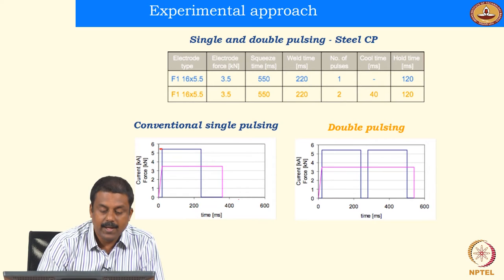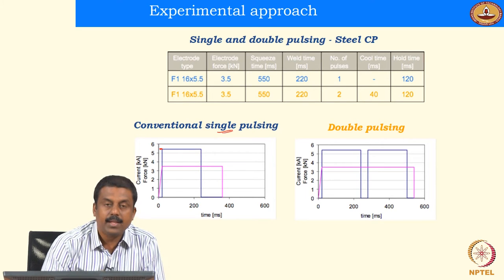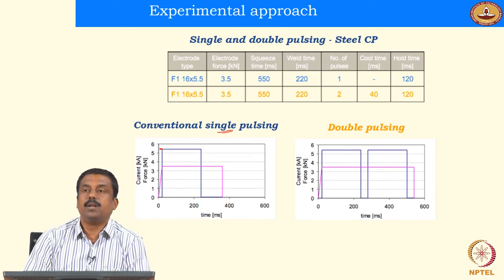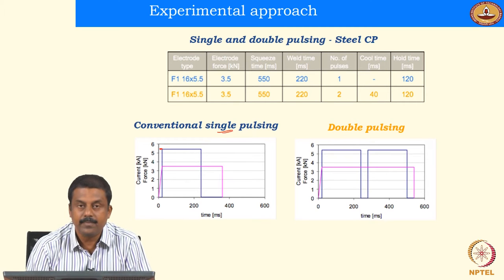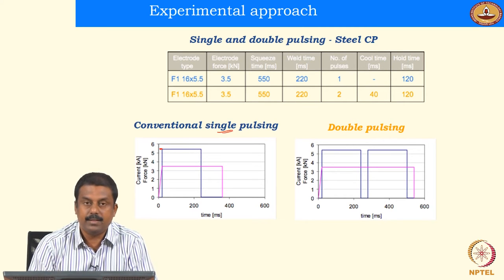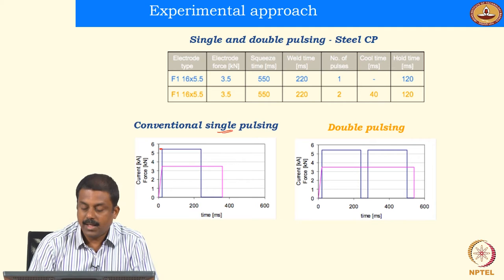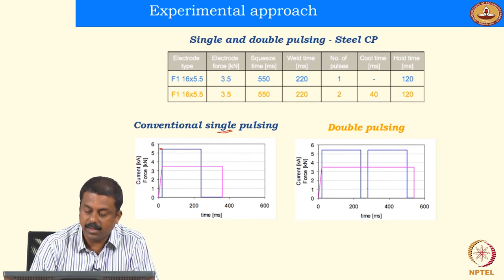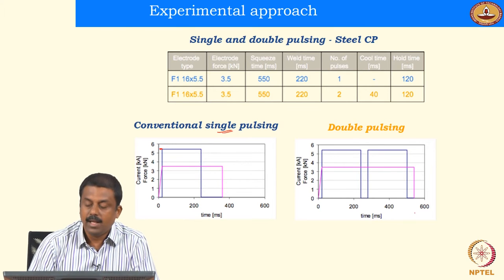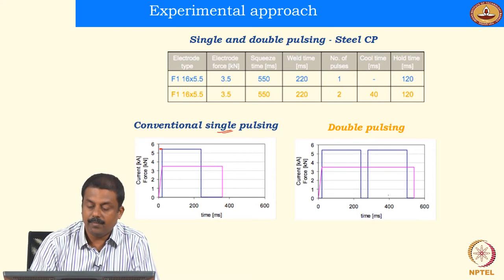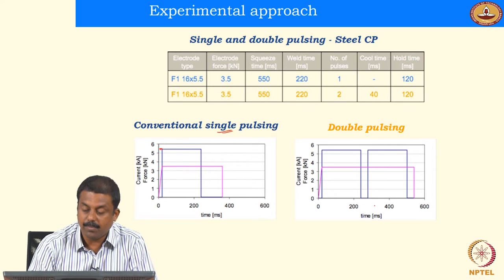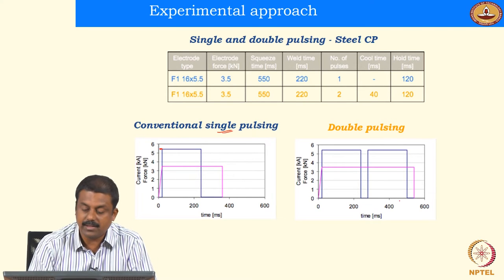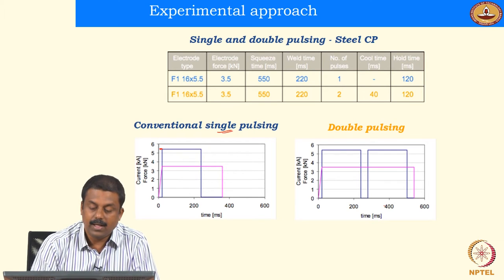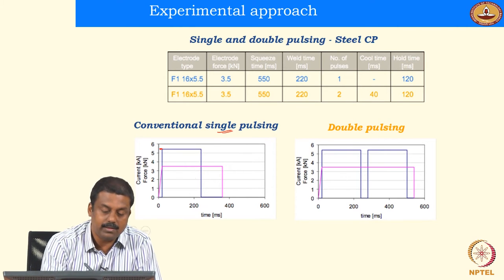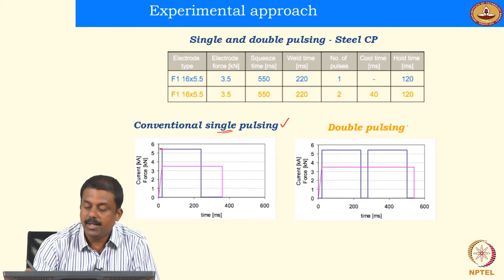So now, instead of doing a single pulsing, in order to reduce the segregation, or in order to homogenize the alloying elements in the weld nugget, we can also apply a second pulsing. So instead of having only a single pulse, we can also apply a second pulse. Whether it is going to improve mechanical properties or not, we will see in subsequent slides. Right now we see the effect on the welding parameters. So instead of using a single pulsing, we do a double pulsing.